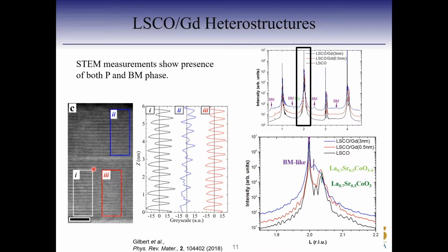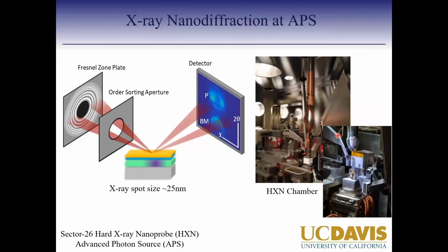So to answer those questions, we utilize a technique called X-ray nanodiffraction, where we can look at as-grown or as-deposited samples without doing any sample prep whatsoever. These studies were done at Argonne National Lab at the Advanced Photon Source at Sector 26. The idea behind X-ray nanodiffraction is you do X-ray diffraction like we're used to in a lab source, except the one key difference is you use a zone plate. This zone plate is a focusing optic for X-rays, and it focuses X-rays down to about a 25 nanometer spot size. That's a very small spot size, which you can then scan over your sample and collect nanoscale information. And you don't need any sample preparation.